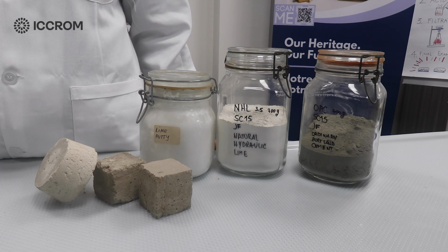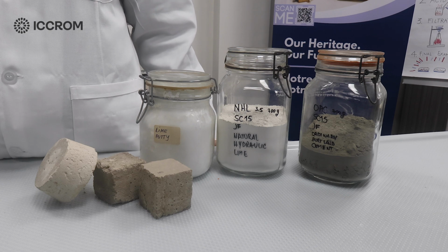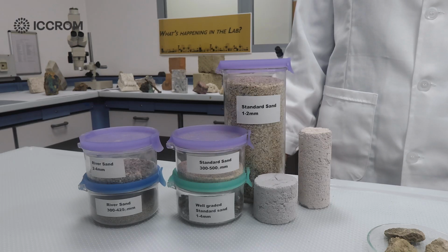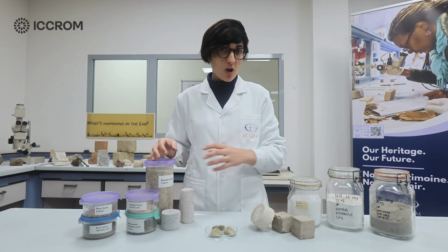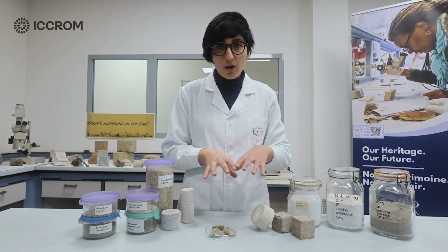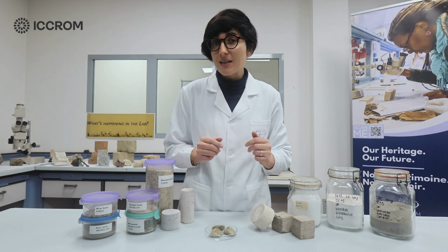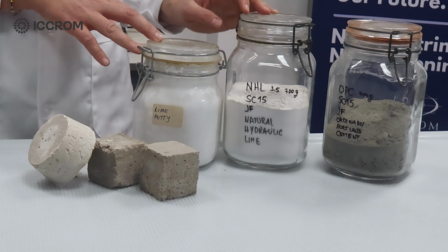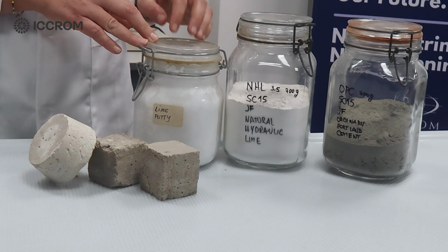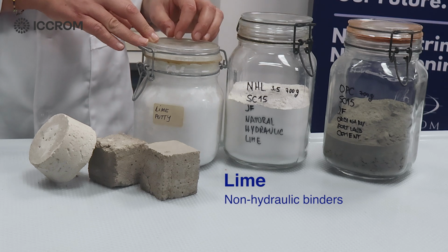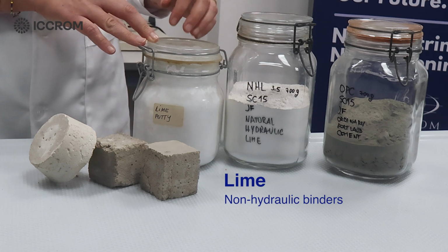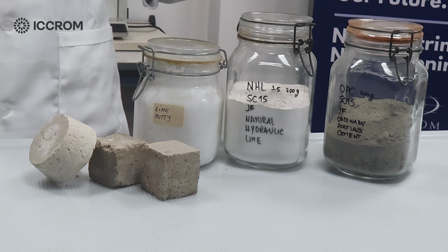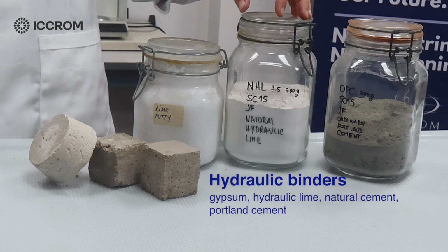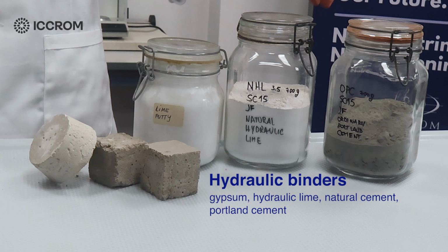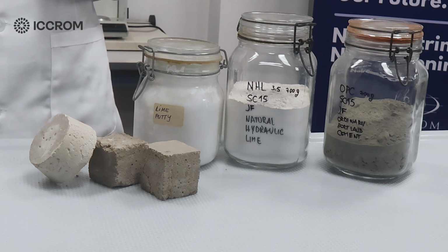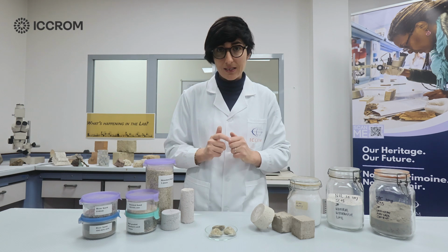Before we start performing the test, let's quickly review the main ingredients that make up a traditional mortar. Mortar is composed of an aggregate and a binder that combine together with water to form a plastic mass. For the binder, there are two common types. We have the non-hydraulic binder, which sets through the loss of water or dehydration, and historically lime is one of the most common ones. And then we have hydraulic binder, which sets and reacts with water. Historically, we have gypsum, hydraulic lime, natural cement, and indeed Portland cement.